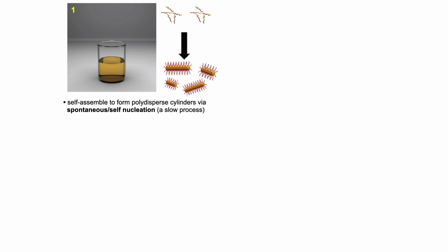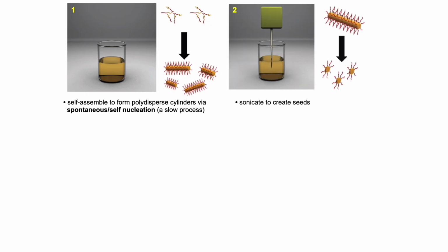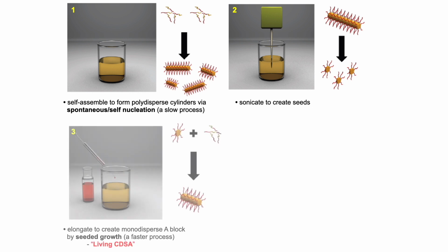So this is how you do it in the lab. You take a solvent, which is good for the corona forming block, poor for the core forming block, and add the polymer to the solvent - it will spontaneously give you fiber-like micelles with different lengths. You then sonicate these, putting a sonicator into the solution. This breaks them down into seeds. Then you take the seeds and add more polymer to them, and you get the controlled growth or living CDSA process to give you your sample.